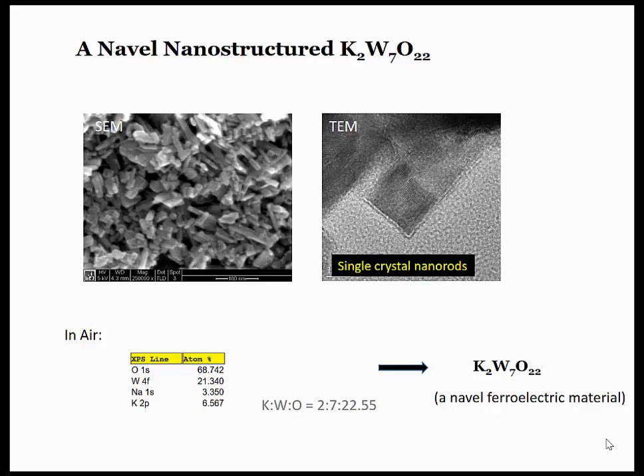We found out the ratio of K, tungsten, and oxygen is 2.7.22. That's why we call this material K2W7O22. That's a new material, which has never been reported before in any of the literature so far.